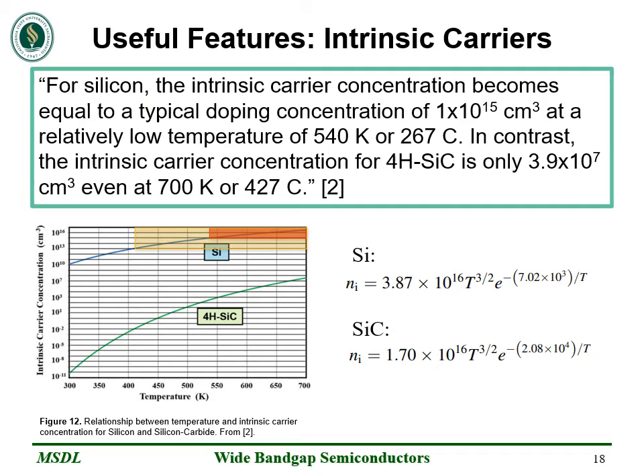So what this means is, let's say I have a PN junction with doping concentration of 1e13 on the lighter dope side. It means I cannot turn off that device above about 410 degrees Kelvin. And even in the example of 1e15, that means I cannot turn my device off above 540 degrees K. It's not possible. The intrinsic carrier concentration is too high. But when we look at silicon carbide, this value only reaches 3.9 E7 even at 700 K. So that means I can operate well above that range and still know that my devices will turn on and off appropriately.